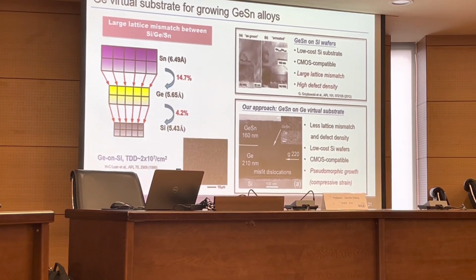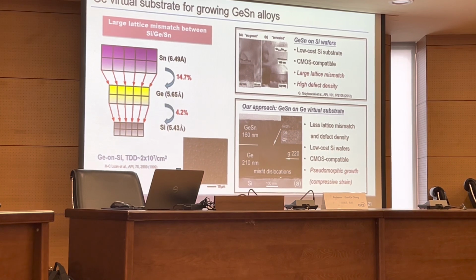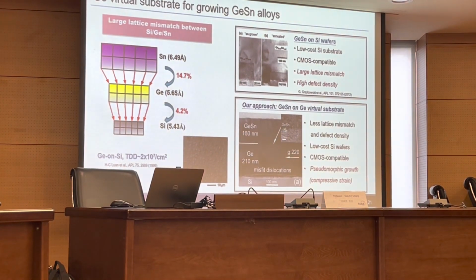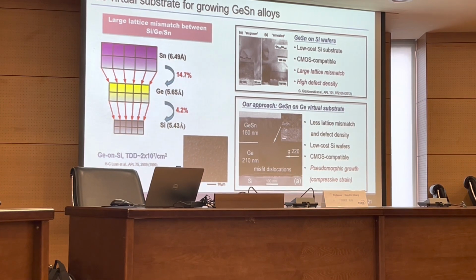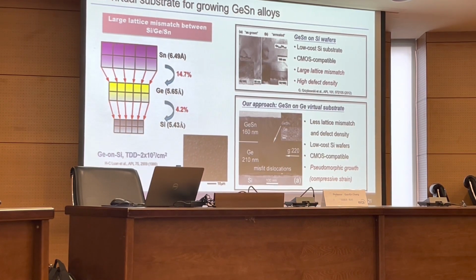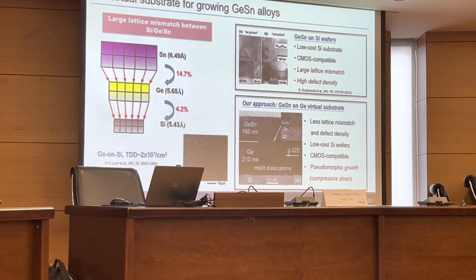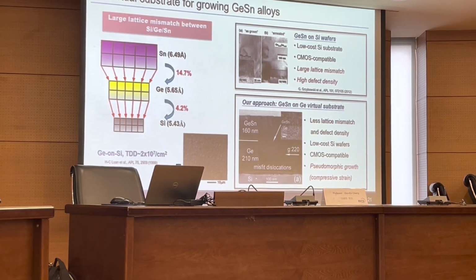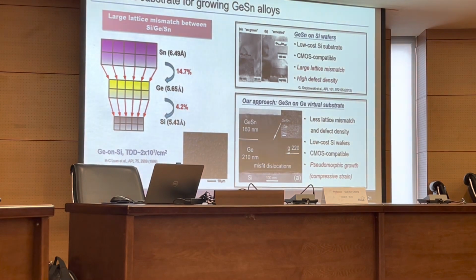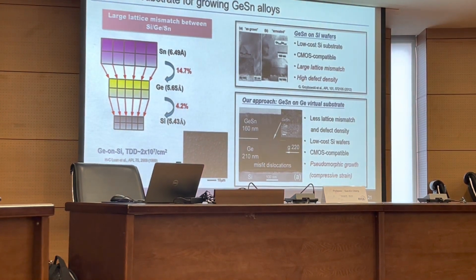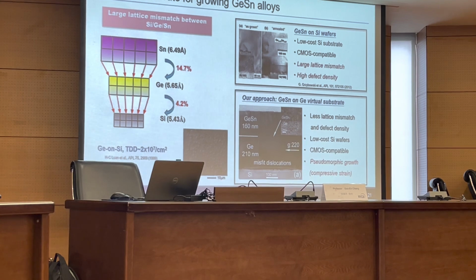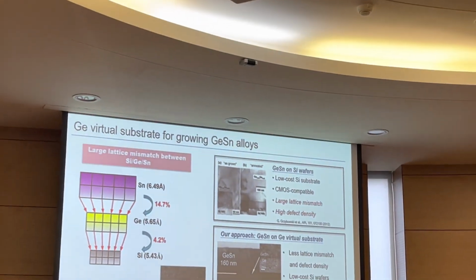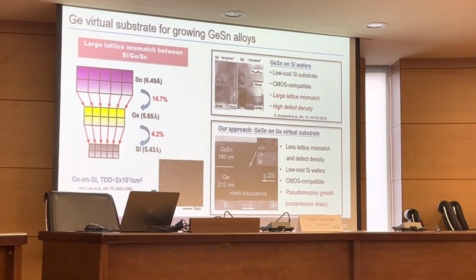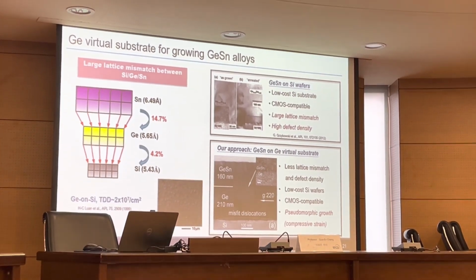So how can we address this challenge? We propose that before we grow germanium, we grow a germanium buffer layer first. By growing a germanium buffer layer, we can localize misfit dislocations near the interface between silicon and germanium. So at the top we have a very high quality surface, and then we grow our germanium-tin active layer. In this way, we can improve the quality of the germanium-tin layer.